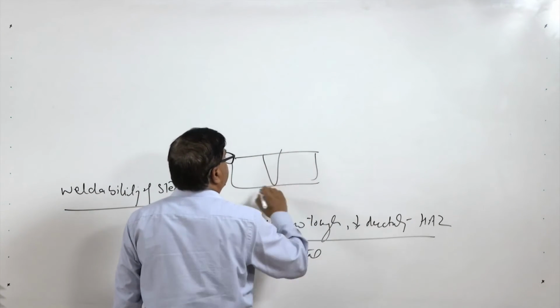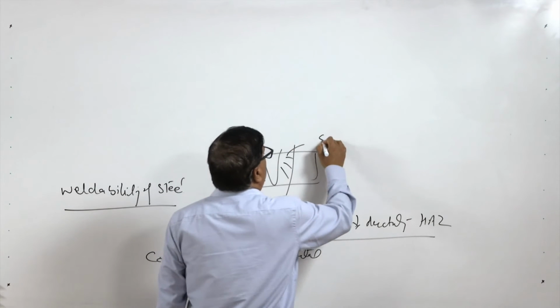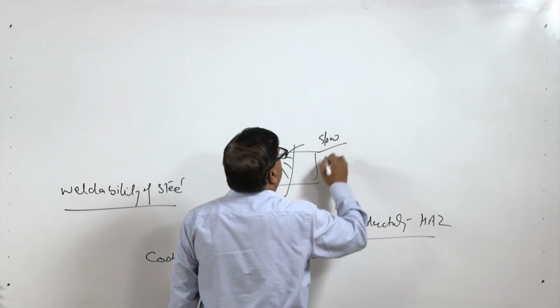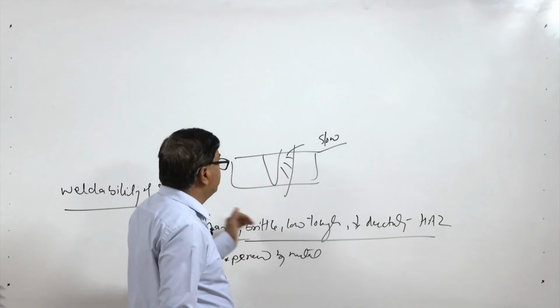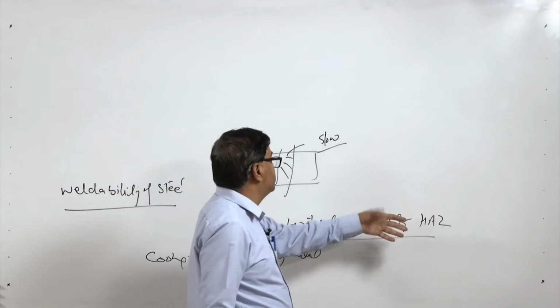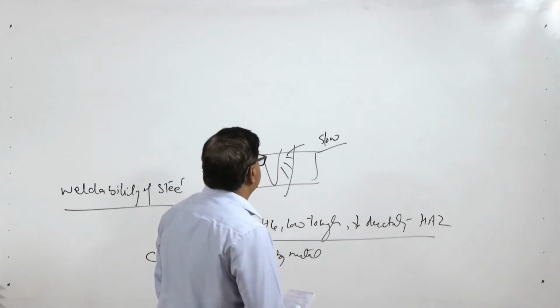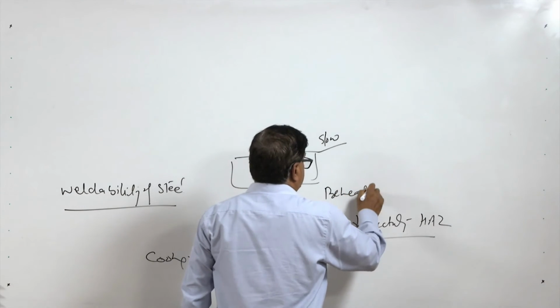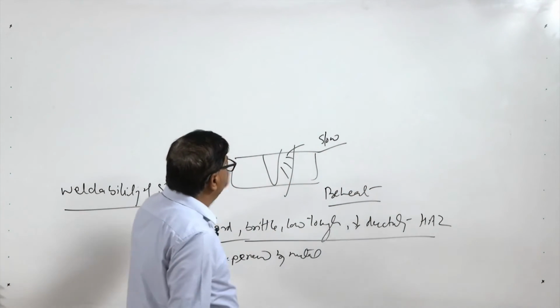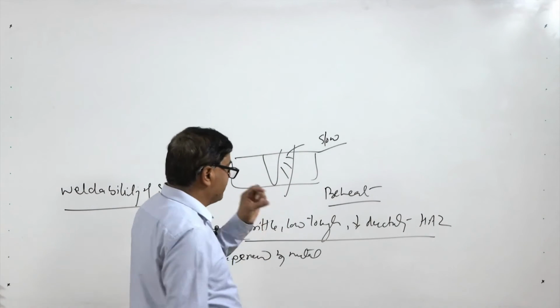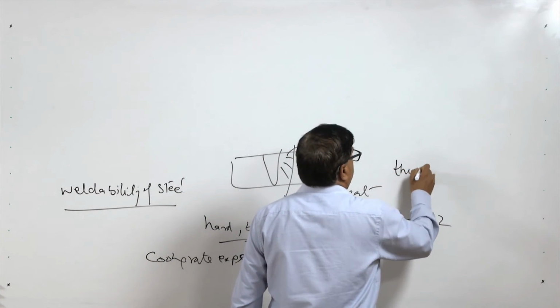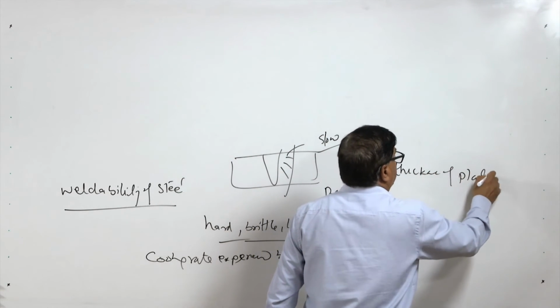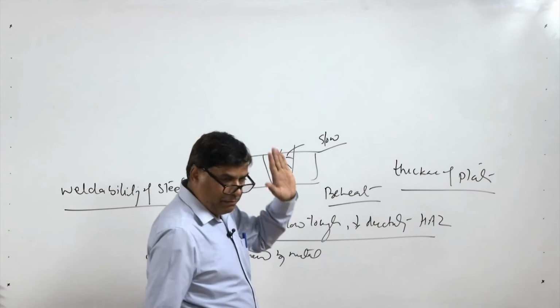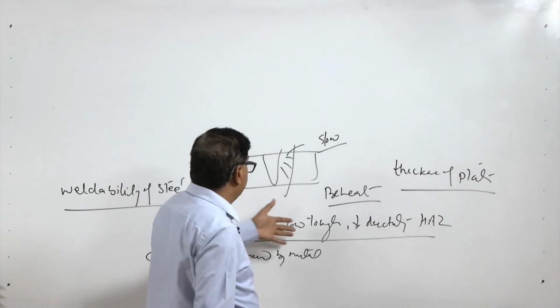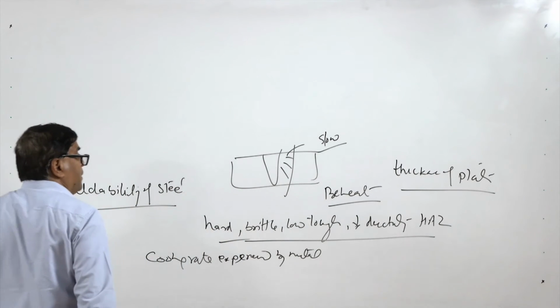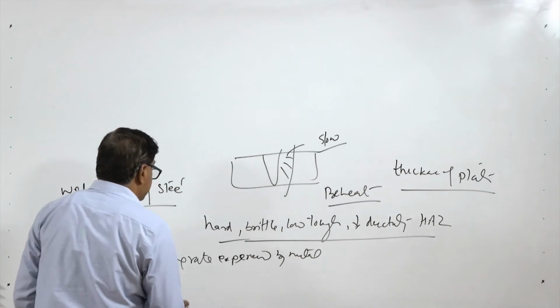For example, like this, the weld is made. So, if the heat affected zone experiences a slow cooling rate, very slow cooling, then the hard, brittle, low ductility and low toughness HAZ is not formed. To facilitate this, preheating is especially done, but the cooling rate being experienced by the heat affected zone is also affected by the thickness of the plate. So, if the plate is very thin, the cooling rate will be low, and in that case the hard, brittle and low ductility HAZ may not form. So, that may not have the cracking tendency otherwise.